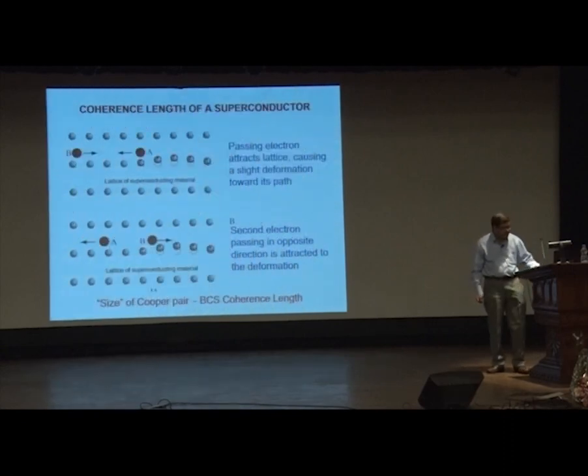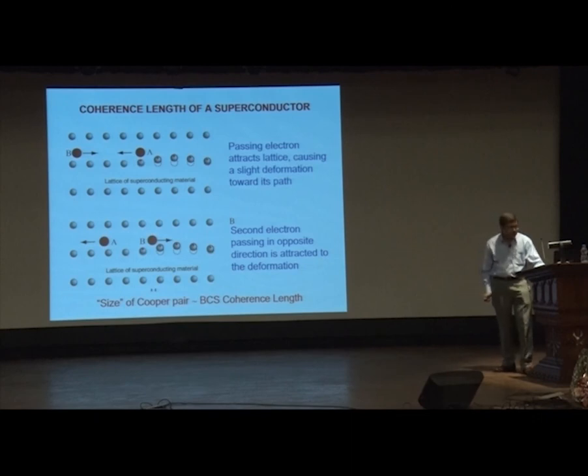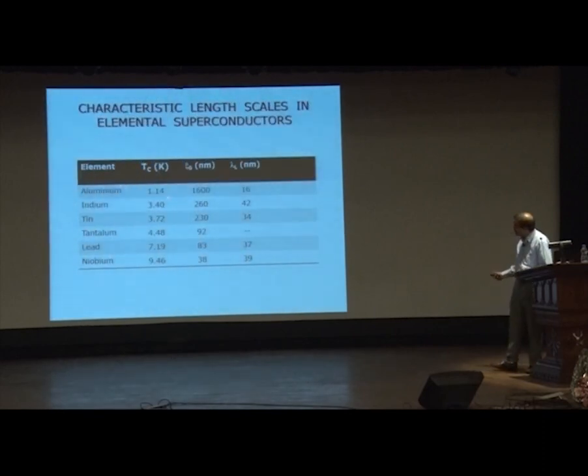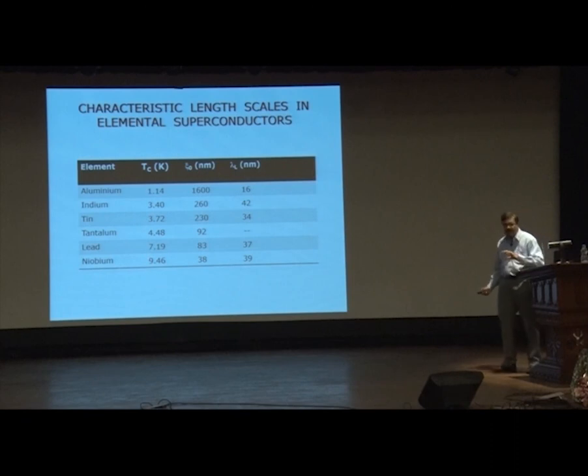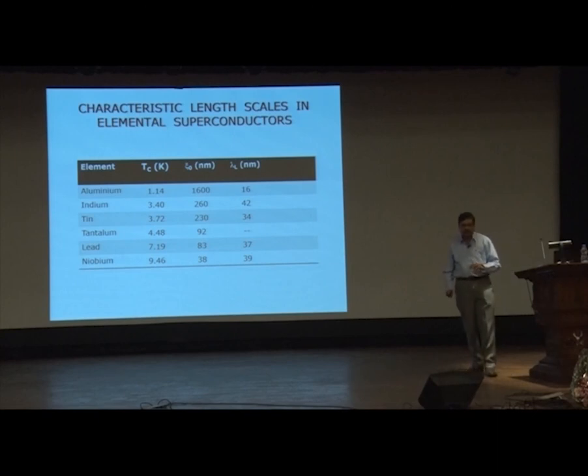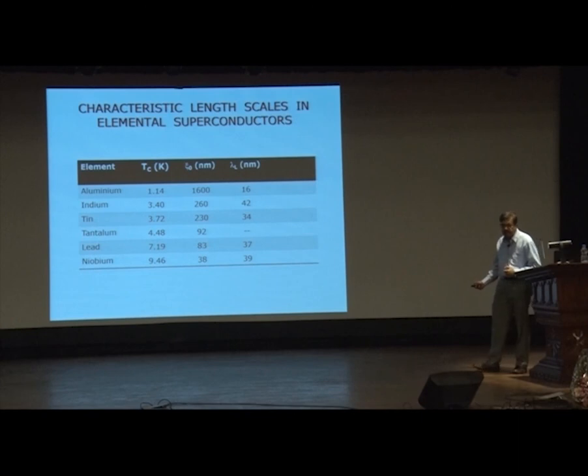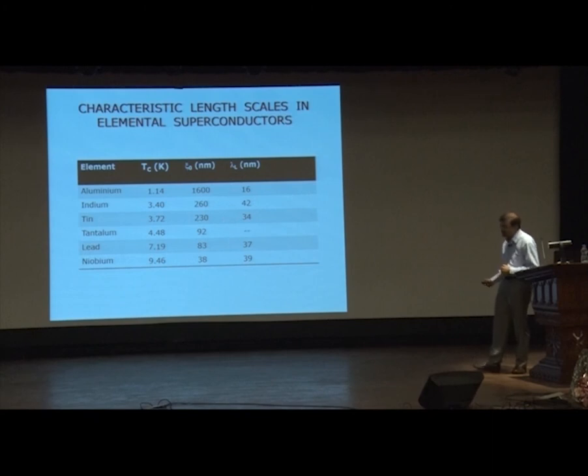The obvious correlation lengths are the coherence length and the magnetic field penetration depth. The coherence length is roughly the size of the BCS Cooper pair, and the penetration depth is just the decay of the external magnetic field within the superconductor. Looking at typical superconductors like aluminum to niobium — TCs in the range of 1 to 9 K — Xi0 shows a large variation but penetration depth does not usually vary too much.